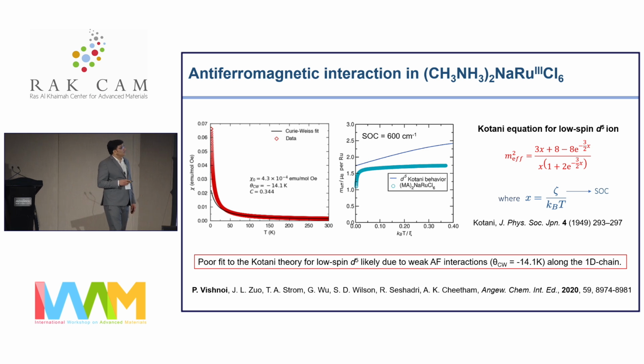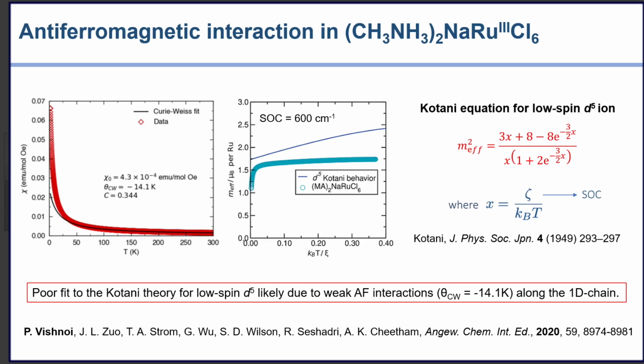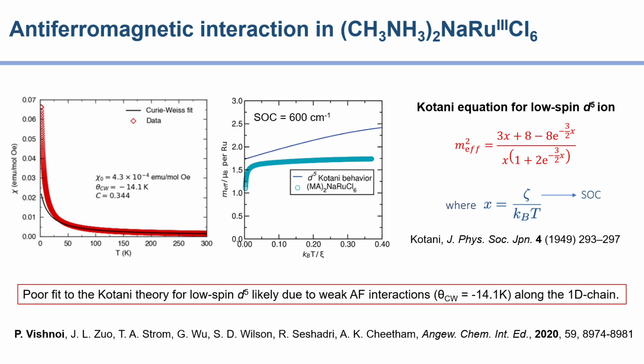One of the motivations to start this work was to find out what the spin-orbit coupling strength is in ruthenium when you put ruthenium metal in different types of lattices. So here, the data can be fitted to a model called the Kotani model, which has a component called spin-orbit coupling strength. By fitting the data, we can extract the value. We see a slightly poor fit because the system is interacting antiferromagnetically.